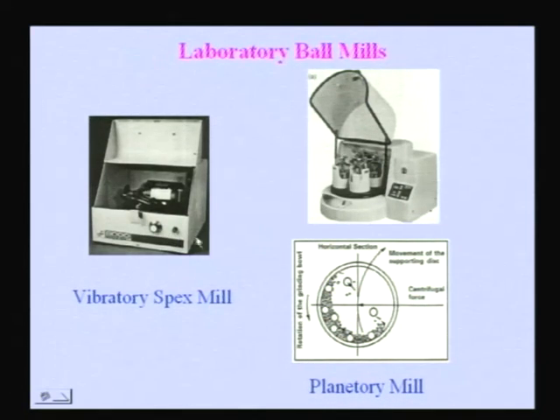So, this is a commercial ball mill called Spex mill. This is an American mill which is very often used, but the only problem with this mill is the quantity of the powder that you can use is very small, not more than about 20 grams. So, if somebody is interested to make slightly larger quantities, he cannot use this kind of mill.